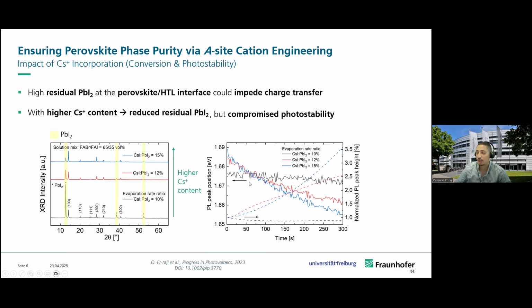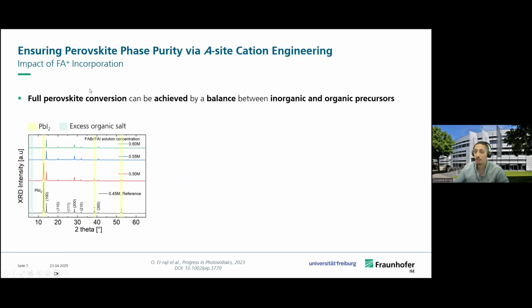On the other hand, when we have a low cesium amount, we have a more stable PL response. So here we can see that cesium not only impacts the conversion level, so the conversion from inorganic scaffold to perovskite, but it also plays a role in photostability, and this should be taken into account. So based on the fact that we do not have a very good photostability at high cesium, we thought that we would stay with a low cesium amount of around 10% compared to lead iodide, and we would then increase the other cation in the system, which is formamidinium.